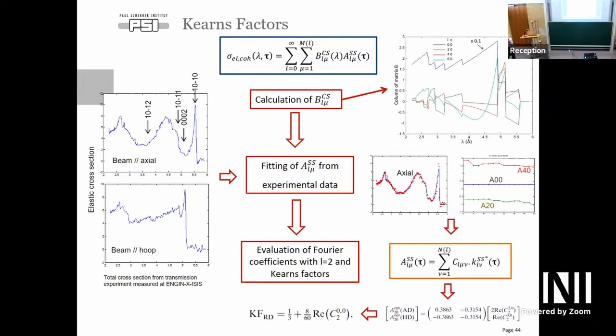Yeah. And so essentially, there's a texture which is more complicated, and you're saying there's a whole heap of things that don't matter. And so this is sort of fitting something which kind of behaves the same, right? Exactly. So basically, for hexagonal materials, the anisotropy is so high in the hexagonal axis, right? So the C axis is exactly this plane, with the 0001 or 0002 itself. So the only thing that you want to know is how these axes are aligned in your sample.